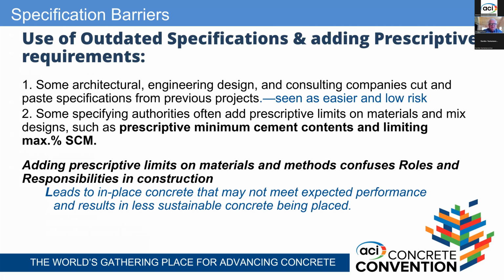Some specifying authorities want performance, but they add prescriptive limits on materials and mix designs. Prescriptive minimum cement contents are not helpful if we're trying to reduce carbon emissions. A lot of these minimum cement contents were based on work that was done 50, 60 years ago, before chemical admixtures and SCMs were on the market. And some of them don't allow the use of supplementary cementitious materials or optimizing for their use, again because of old prescriptive specifications that have been there for decades.